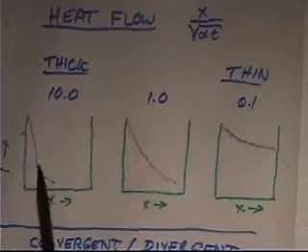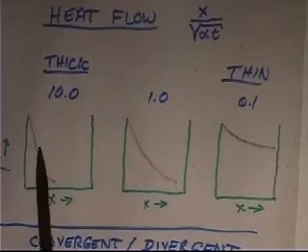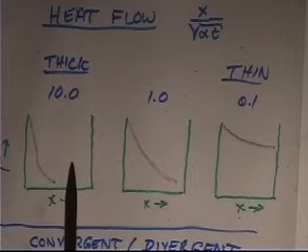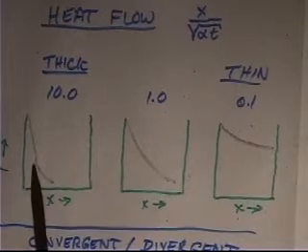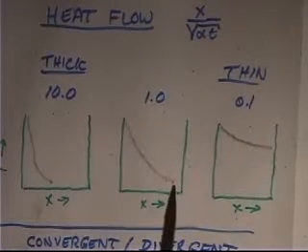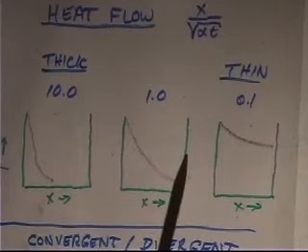Okay, I have maybe 1/5 or 1/10 of my material in compression, which has to be distributed over the other 80–90% of the material, which has to go into tension, which means the tensile stresses out here in the cold material are 1/10 or 1/5 the value of the compressive stresses here, because the stresses have to equilibrate. Everybody following what I'm saying there? If I'm like this, somewhere near a Fourier number of 1, I have absolutely the worst possible tensile stresses on the outside of this vessel.